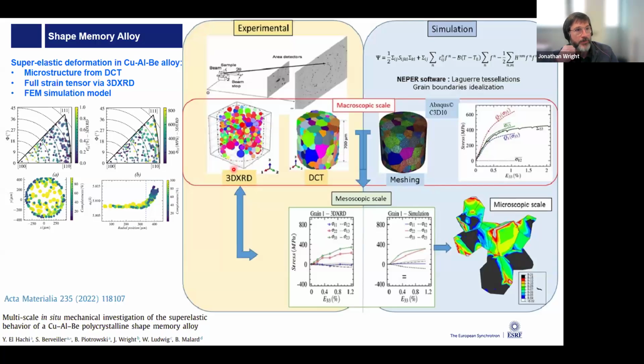So another example with the grain mapping methods, this time from metallurgy, from Eunice El-Hatchi, Sophie Bervier and co-workers. So this is a shape memory alloy. It's a copper aluminium beryllium in this case. And so when you stretch or deform this alloy, it has a large elastic response, and then eventually it goes through a phase transformation, and that gives this famous shape memory effect, where you can deform the metal and then heat it up and it will come back to its original shape.